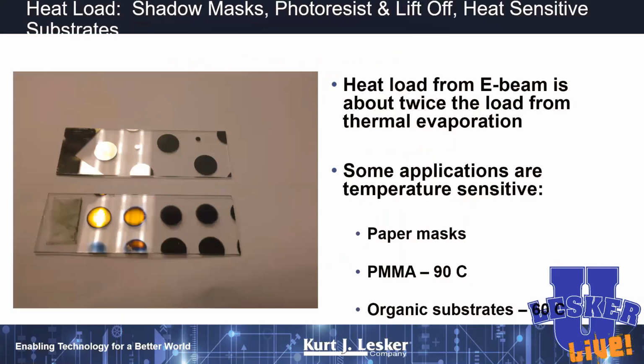Now, I talked about heat load before. Again, these are images from Case Western Reserve University. When they were trying to do contact pads on a microscope slide with a plastic mask by E-beam, you can see that they actually made some decent pads here. Everything looked great. Then they tried to use a paper mask, and the heat load on the paper mask was way more than the paper could handle. It outgassed a lot, and so they formed things like silver oxide here. The paper warped, and so they got maybe no films formed at all, or very, very horrible resolution there.